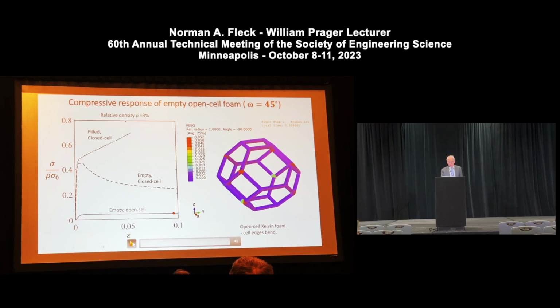So when the material is deformed, plastic hinges form, and geometric hardening or softening can occur. In this case, geometric softening occurs, and that can lead to crush band formation. So that's the open cell foam. That's well known. Gives our reference.